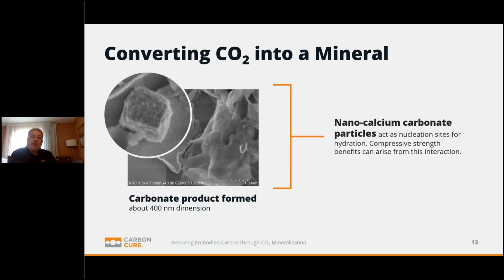So when we convert that into a mineral, basically what happens is we create these nanonucleation sites. So think what happens when you have a magnet and you've got little shavings of iron particles, it basically attracts. The same kind of thing happens here: when we inject the CO2, those nanoparticles start to create nucleation sites, and that's actually what gives us the compressive strength gain that drives the mix design optimization that we work on. And this is just an example of a scanning electron microscope image that actually shows what that looks like.